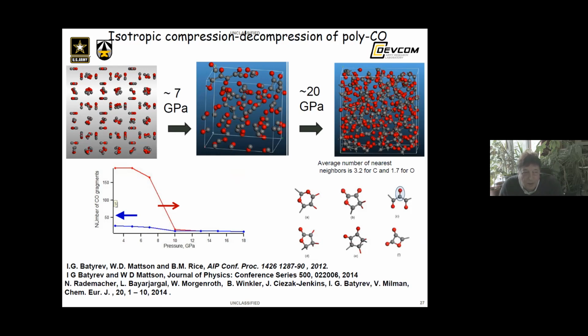If we release the pressure down to 1 GPa, the covalent network would survive and represent a material with high density and energy content exceeding conventional energetic materials. Obviously, there is evidence of pressure stabilization of the polyCO covalent amorphous structure. So almost all intact molecules are included in the network.